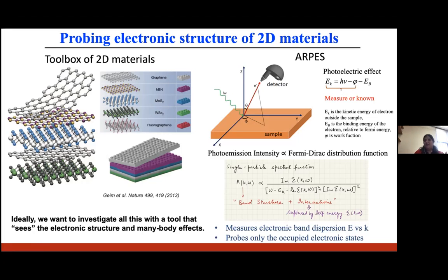Now, I don't have the time to go over the theory of the photoemission process, but I want you to keep in mind 2 important things. The first one is that the photoemission intensity is directly proportional to the Fermi-Dirac distribution function. And secondly, the single particle spectral function in ARPES gives us the band structure and the interactions. And here the interactions are captured by this imaginary self energy term, okay? And I'll come back to this later in my talk, where I'm going to look at this imaginary self energy term in the single layer graphene.